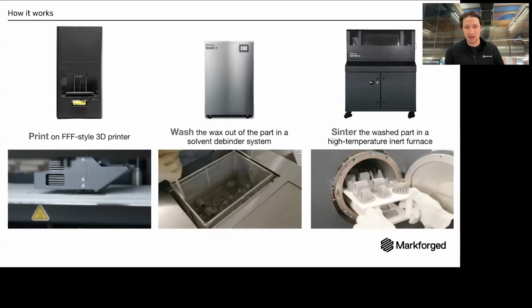We provide all the machines. A couple extra notes here. You can print solid parts on it, but the geometries that work best tend to be thinner. The reason is that if you print solid, the time it takes to dissolve through the binder goes up exponentially. That's one caveat. To combat that, we print what we call open cell infill, pretty similar to your conventional 3D printed parts. You have walls, floors, and then you have some infill lattice structure. That enables the debinding fluid to permeate a lot more easily and a lot faster. We'll get into print times and time in hand for print, wash, and sinter for some parts in a bit, but that's an idea of the process.